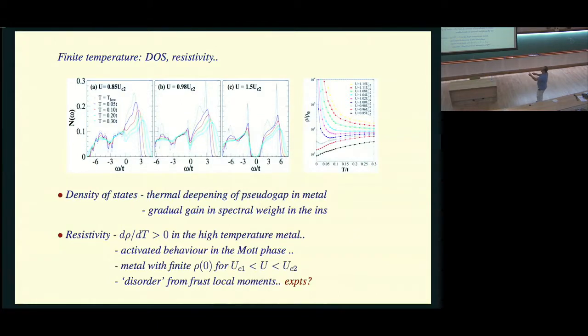So this is to say that if you probe the spectral features in the transport by your sampling procedure, you get a pseudo gap which deepens with increasing temperature in the metallic phase. You get a gap which smudges out with increasing temperature in the insulating phase, and you can look at angle resolved spectral functions, optical conductivity, etc. So the upshot of all this is there seems to be a disorder arising from the emergence of frustrated local moments in this kind of a model and this kind of an approximation.